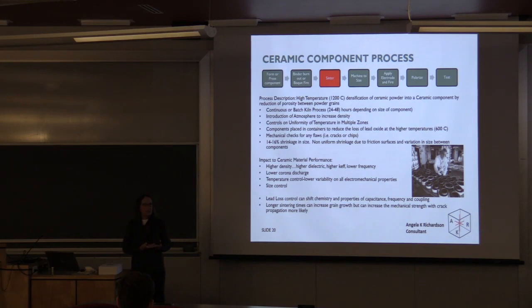So what happens is at about 600 C, your ceramic is going to soften. You're going to start to evaporate lead. Well, if you started with a composition of a particular amount, if you're losing lead to that kiln, what you're going to get is something different than what you planned to create. So 14 to 16% shrinkage, typically, watching the grain growth. Obviously, we want some grain growth, but not to the adverse effect of mechanical strength.